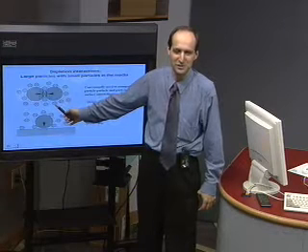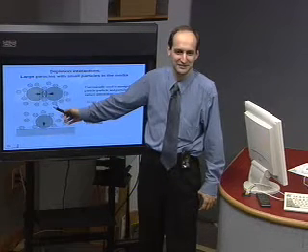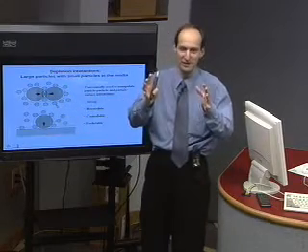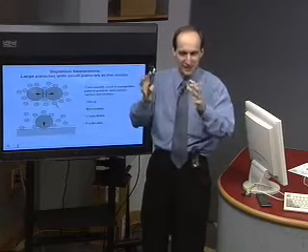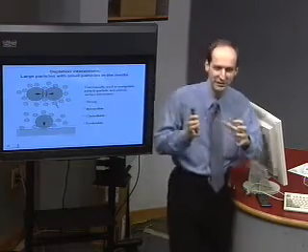You're going to reach what's called the jamming limit. Essentially, if the particles are the same size, they eventually freeze at some point, which is the jamming limit, about 0.64, just because you have so many of them that they repel each other. But typically 1 to 10, 1 to 20, 1 to 50 would be a good size. So it's a very useful, easily controllable force.